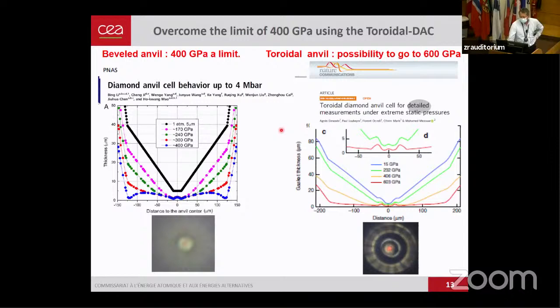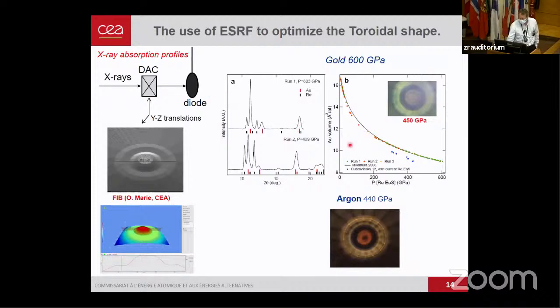two devices were proposed lately. One by the Dubrovinsky group, putting a little ball of diamond on top of the diamond tip, and we designed a new kind of tip, which we call toroidal, that we could make by using a FIB machining of the diamond. And with that, we could show that the sample was not changing compared to what we were having in standard diamond cell. And we could reach, on gold, on argon, at least 600 GPa.